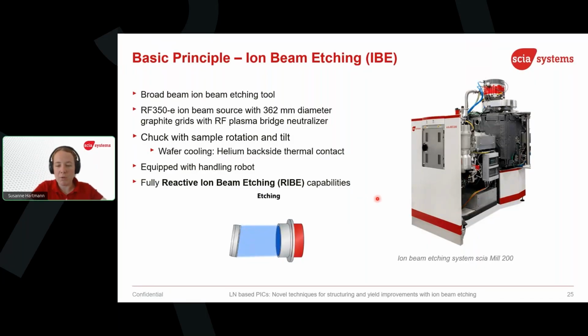Coming to the ion beam etching, on the right-hand side, we see the tool that is used for this application. We again see the load lock on the left-hand side, where the cassette has been placed. We see the transfer module, where the wafer is aligned, and we see the main chamber. On the top, we see the turbo pump, because of course the machine is in high vacuum. What we do not see is the ion beam source, which is pointing to the backside. What you can see in the animation is that the wafer is handled in horizontally, first from the handler, and then it can be rotated to arbitrary angles. For example, it can be etched at a perpendicular angle between the ion beam source and the wafer, or it can be etched at any arbitrary angle, which we will see later.